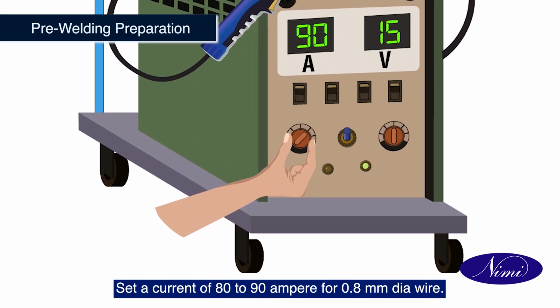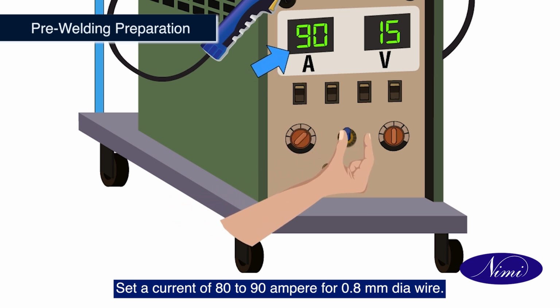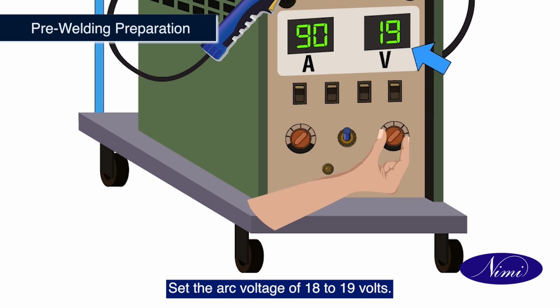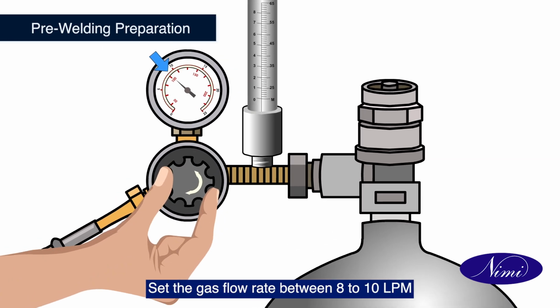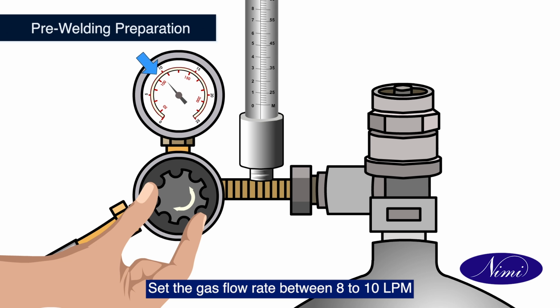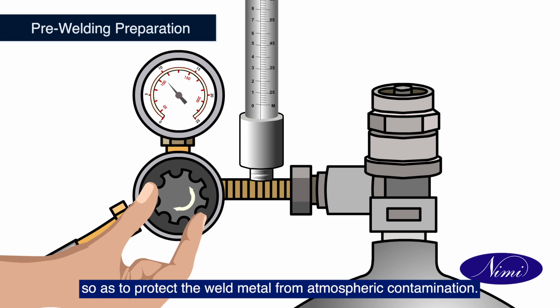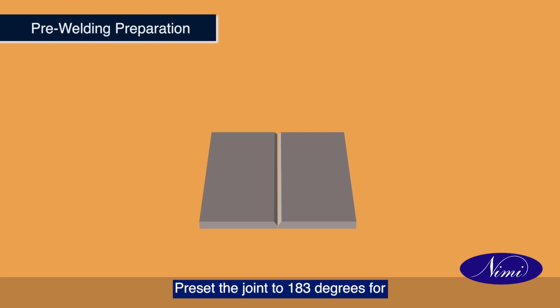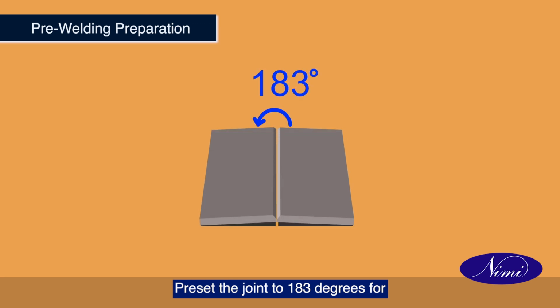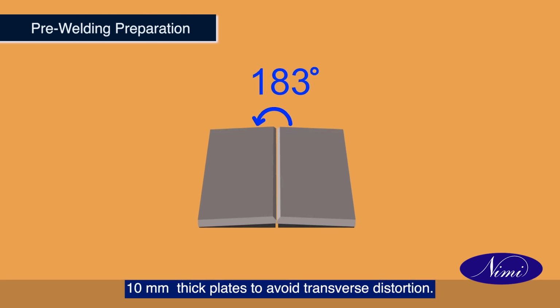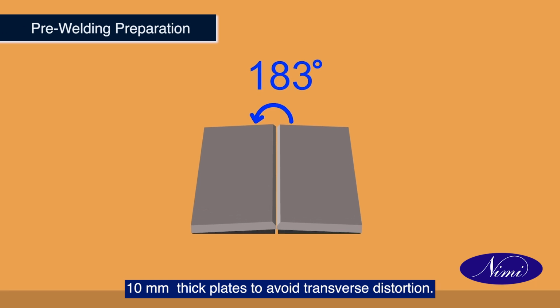Set a current of 80 to 90 ampere for 0.8 mm dia wire. Set the arc voltage of 18 to 19 volts. Set the gas flow rate between 8 to 10 LPM so as to protect the weld metal from atmospheric contamination. Preset the joint to 183 degrees for 10 mm thick plates to avoid transverse distortion.